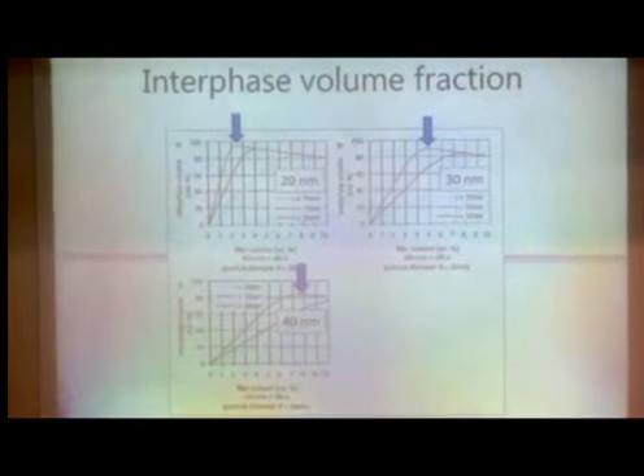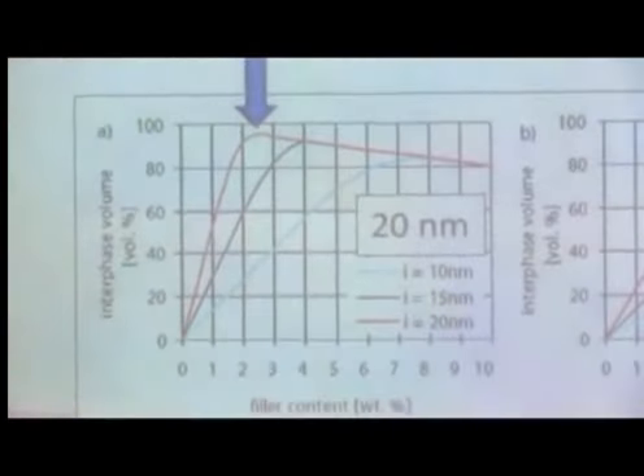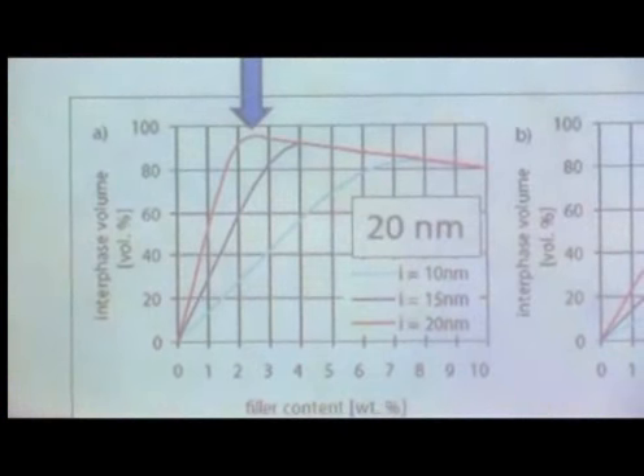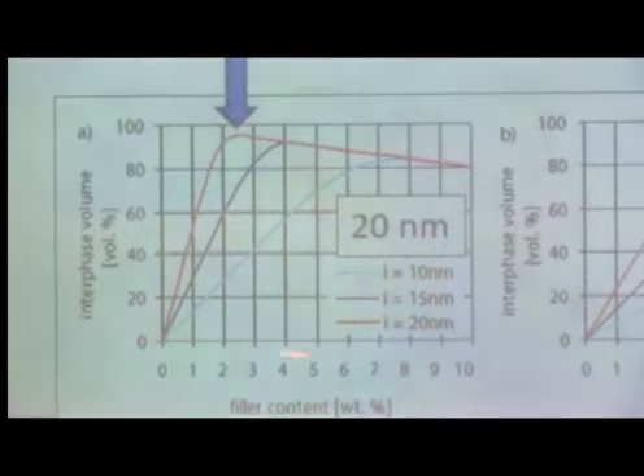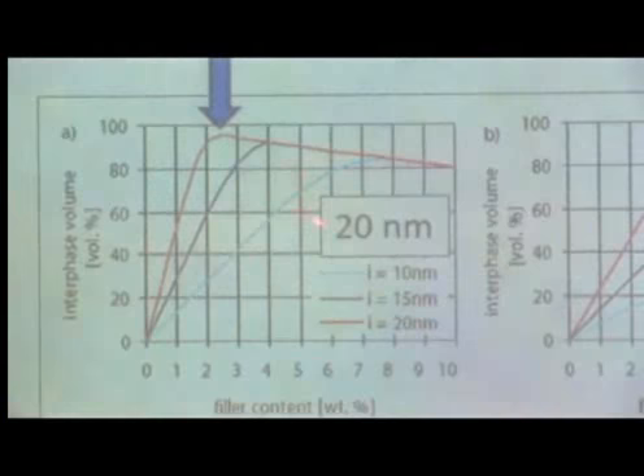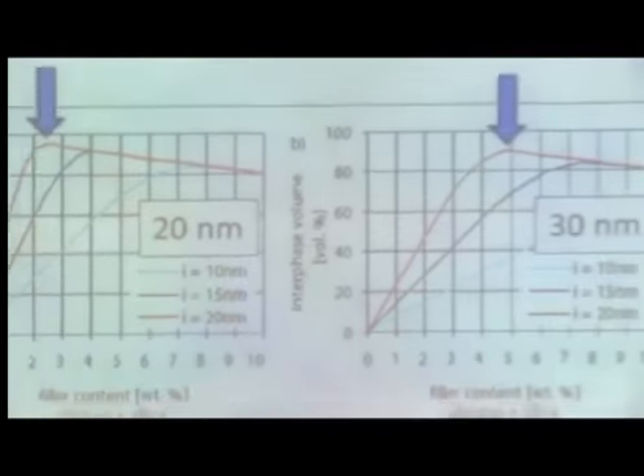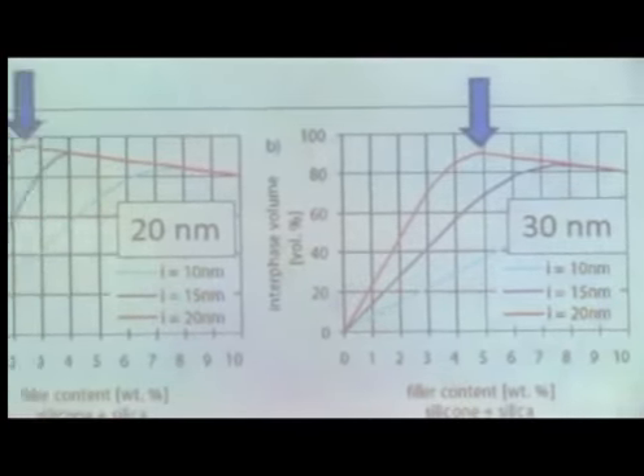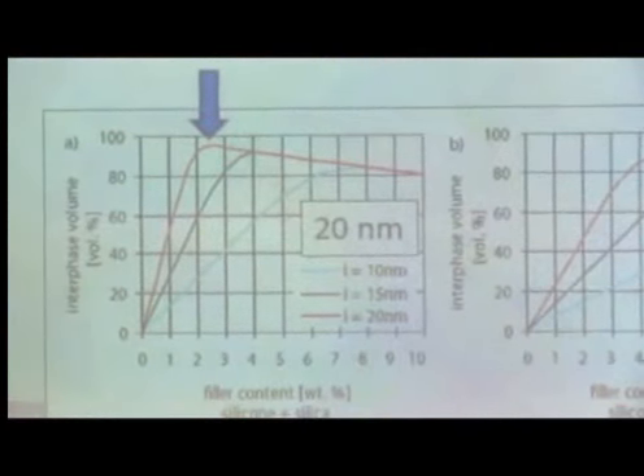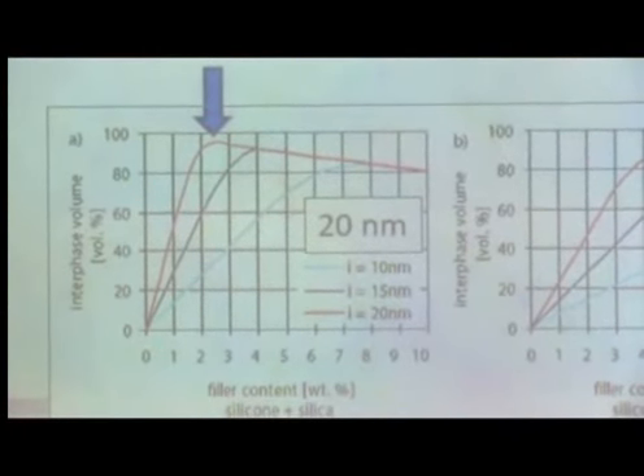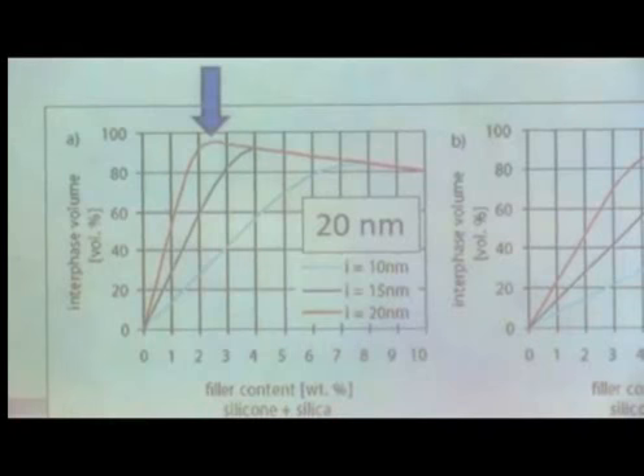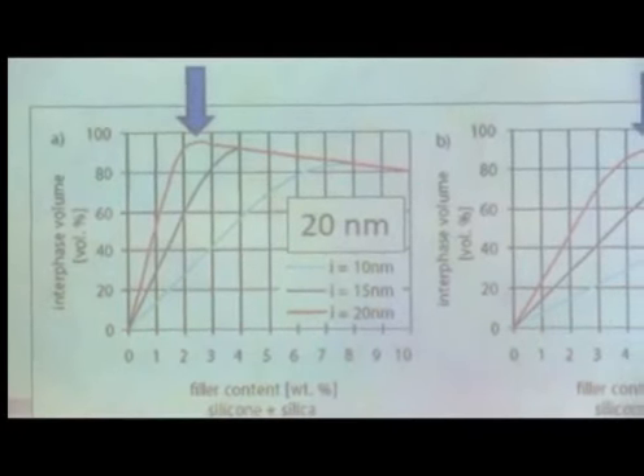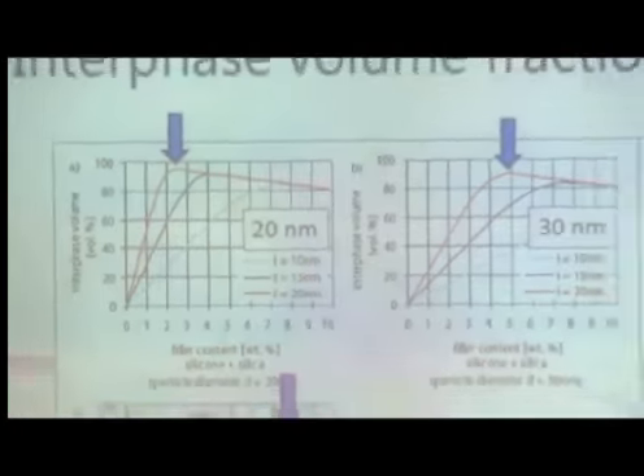Let me show you. These are plots from Stephanie Retzke, where on the y-axis all the time is the interface volume, plotted as a function of filler content. This is weight %. And then for different size nanoparticles, 20, 30, and 40 nanometers. And you see, follow the red lines, that there's a peak in the amount of interfacial volume. Meaning really that if you add more nanoparticles, the interfacial zones are going to overlap, and you don't get any more.